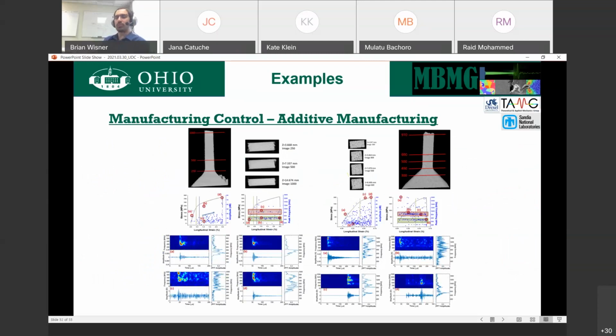Well, we can throw everything we have at this: X-ray analysis, acoustic emission, looking at the different AE features we see. And we notice there are some similarities between these two materials, but there are some differences. And what's essentially happening is, in the case of the optimum configuration, there is a single weak point that is dominating its behavior. So while it's optimum, you have one primary location that's going to fail. Whereas in the case of non-optimum, you have a lot of nucleation zones. You have a lot of voids that could lead to failure. And what's happening is a number of them are fracturing. So you have many locations where cracks are growing and stopping as they interact with other voids.